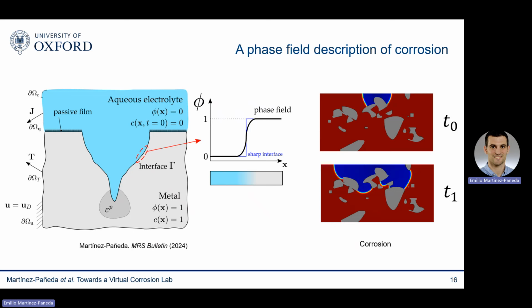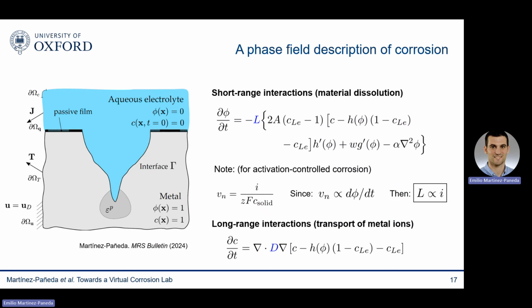So the phase field is going to act as a marker, and it's going to tell us where the corrosion front is, basically by taking a value of 0 in the electrolyte and a value of 1 inside of the metal. And throughout my talk, I will use blue color to denote electrolyte and red color to denote metal. I'm going to skip all the mathematical details for the sake of time, but if anyone is interested, this is all derived from a free energy functional, so all is based on thermodynamics, and the constitutive choices are based on the so-called KKS, Kim-Kim-Suzuki model, which assumes thermodynamic equilibrium between the phases.